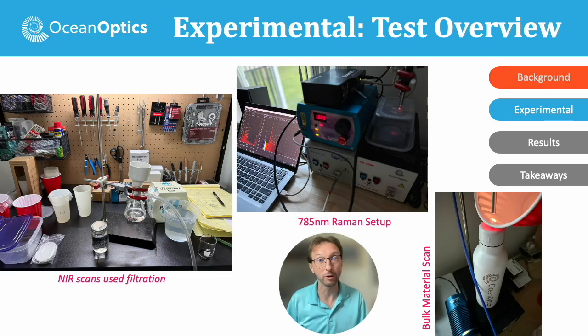Here are a few photos from our test that we ran, or at least the experimental setup. So for the near-infrared scans here, we wanted to use a filtration technique, because you're going to see in the plots here shortly, the UV activity is much more pronounced. So UV is much more optically active compared to near-infrared signals, which just inherently aren't very active. So to get a usable signal, we figured we would take that bulk liquid and run it through a small filter and then compare that. So a filter that's just filtered the clean fluid compared to a filter that had the leachant fluid filtered through it, and then comparing those with a reflection setup. So that's how we did it for the NIR. Otherwise, we just looked at the liquid straight away using ultraviolet or Raman.